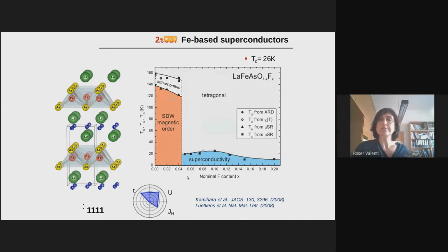So now if we want to describe these materials, again, through our four interactions, what we would have here is, again, the hopping term of our itinerant electrons. In our case, the itinerant electrons are the iron d electrons. We have Coulomb repulsion. These are 3d electrons, so there is a Coulomb repulsion. But in our case here, we also have an important Hund's coupling term because we are dealing with multi-orbital sites. So therefore, there is a new interaction entering into the game for the description of these iron-based superconductors.